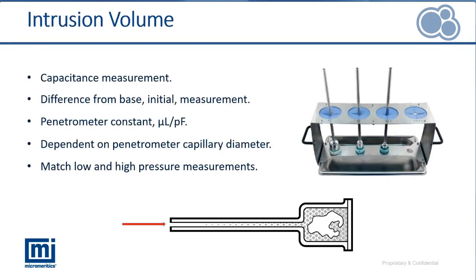Now we do this because we know a penetrometer constant. That's a value that will convert change in capacitance to quantity of mercury. So we take an original first capacitance measurement, and then for each data point, that's basically zero intrusion, and then for each data point, we just measure the capacitance as well as the pressure to calculate the pore size distribution.